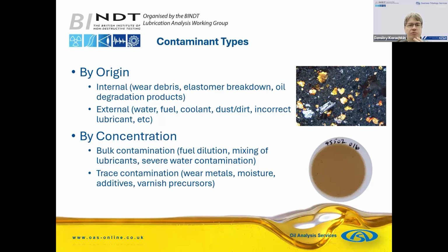But we sometimes need to look for contaminants which are present in very, very small concentrations. So trace contamination, this can be wear metals, moisture again. Some systems are very sensitive to water content, so being able to detect it at a very early stage, at very low levels, like we were saying earlier, parts per million rather than percentages, and sometimes even 70 parts per million in an application may be considered too high. But also ingress of additives as an indication for different lubricant getting in, and the varnish precursors as well. They're present in small quantities, but they can cause various problems.